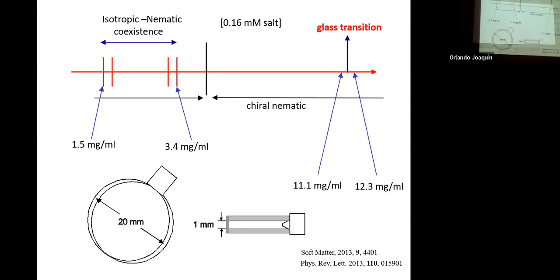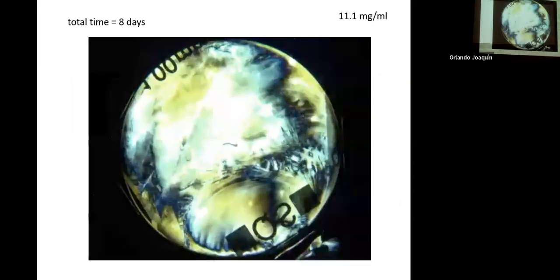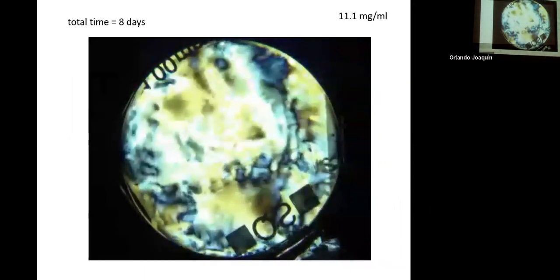So I'm first going to look at a concentration of 11.1 milligrams per ml, which is relatively low, and then 12.3, which is just above it. There is only a small difference, but the behavior is completely different. So you fill the cuvette, put it between these polarizers, and think about what happens—and this is what happens.